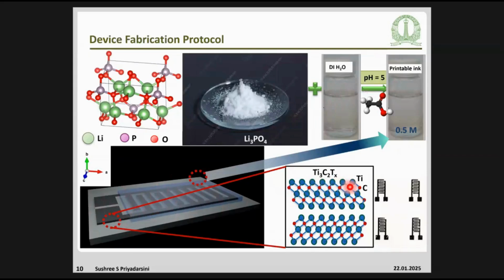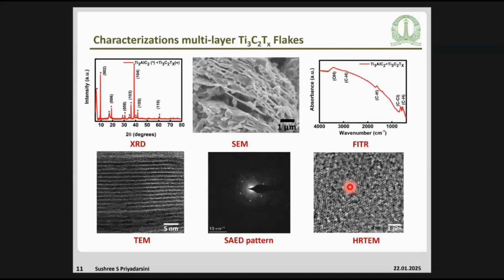And then next is the characterization of the electrode material. So as you can see from the XRD, it is clearly visible that you have both the phases, not only the multi-layer titanium carbide, but along with that titanium aluminum carbide also. When we see it in SEM, I mean scanning electron microscopy, we saw that the accordion structure is present. To understand what bonds are present here, we have done FTIR. There you can see OH hydroxyl groups, CH groups, and Cl groups are also present.